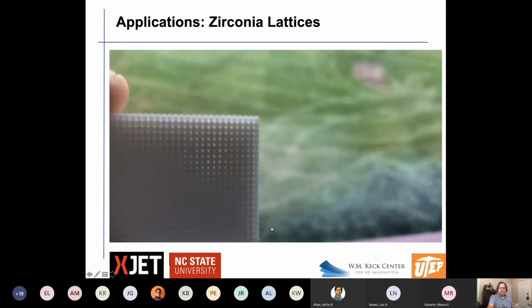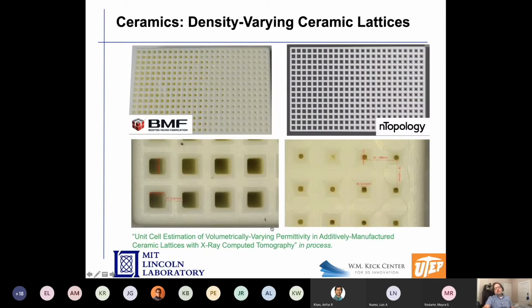And what's cool about this, and maybe I could show it here, is I can spatially vary those. So over here, you can see that same lattice spacing is there, but it's much thicker. So the ratio of zirconia to air is much higher than over here, where it's more air and less zirconia. And it turns out that when you do that, the effective permittivity can be changed from one side to the other, which means you can change the speed of light from one side to the other. And there's just some fascinating applications of this, really, to do lenses.